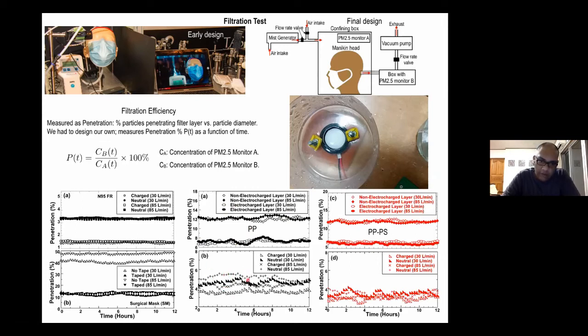The plot below where my spotlight is hovering right now is for the 3D printed mask with the electrocharged layer using charged and neutral aerosol particles. And you can see that almost all of them, except for the neutral particles at 85 liters per minute, were below the 5% mark. The neutral particles at 85 liters per minute crossed the 5% mark, but the other three were below it.